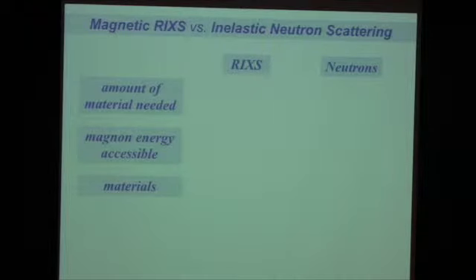So talking about neutron scattering and RIXS, let's compare. I have three sets of issues that I want to compare. First of all, is the material needed. For neutrons, I've written down large. For inelastic neutron scattering, you need samples in the order of grams. RIXS, actually, some of the data I've shown you was done on thin film cuprates. My experimentalist friends tell me they can do RIXS on a single copper oxide layer if they want to. That's something that neutron scattering will never be able to do. So RIXS is very good.